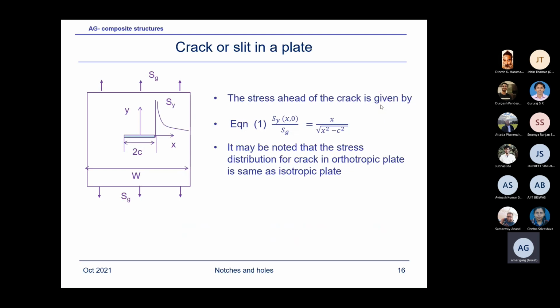Next is the stress distribution for the crack. Similarly, we have sigma_g, the gross stress. So I have written here sigma_y at (x, 0), at y equal to 0, is equal to sigma_g times x upon root of x square minus c square. This is from fracture mechanics considerations. Now, what you would notice, this functionality for stress distribution is not dependent upon anisotropy. There's no anisotropy term appearing in this, whether it's isotropic or anisotropic, the behavior seems to be the same as far as the stress distribution is concerned.